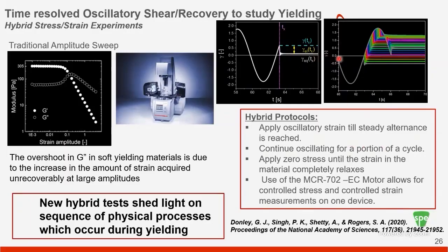And this is a very unique experiment where, in a typical oscillation cycle, you're stopping at different instances in an oscillation cycle and creeping to zero stress. So you need a device which can actually switch from strain to stress control seamlessly. And here again, the multi-drive device with the EC motor, the electronically commuted motor, really does a great job because it allows for this controlled stress and controlled strain type measurements on one device.